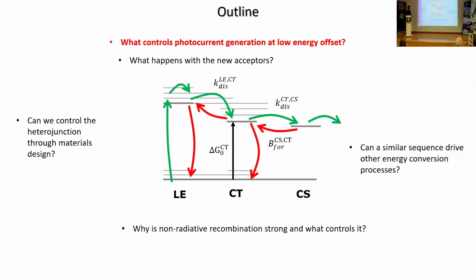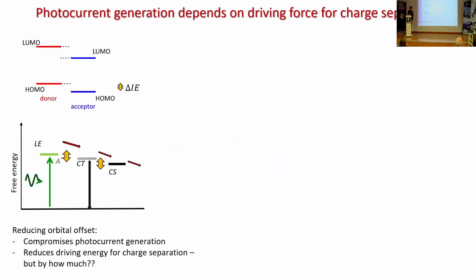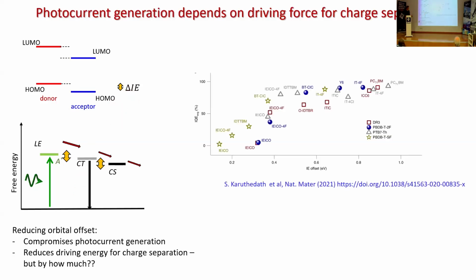So I move on then to the next question about photocurrent generation. If we only think about the last topic, which is the voltage, the voltage is going to be higher the higher the energy of the charge transfer state is, and that means the smaller the offset in energy levels between the frontier molecular orbitals of the donor and acceptor. So if you have a given set of materials, and you could play with the offset, then if you just think about voltage, you want the smallest possible offset, and that should be the best condition.